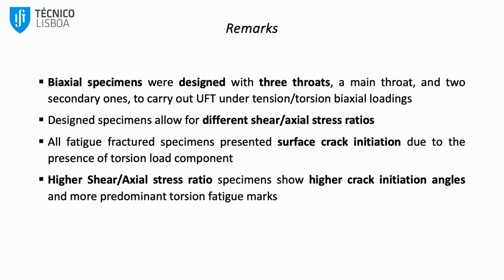So we have produced biaxial specimens, with 3 throats, that allow us to perform biaxial loading tests in very high cycle fatigue. We can produce tests at different stress ratios. And in this case, due to the shear component, all the crack origins were at the surface. And also the higher stress ratio is linked to higher crack initiation angles and more prominent torsion fatigue marks.